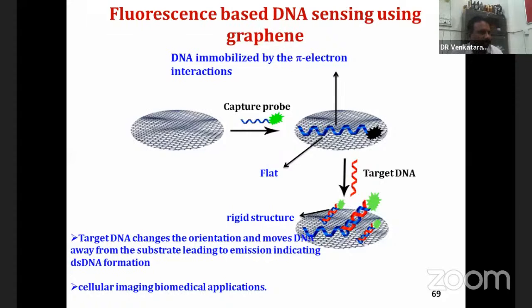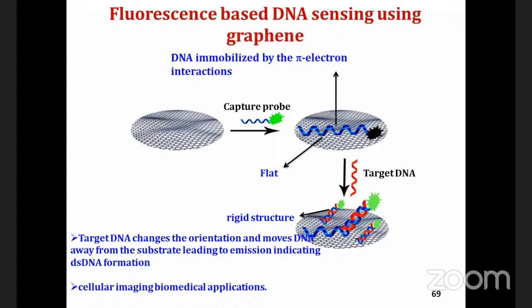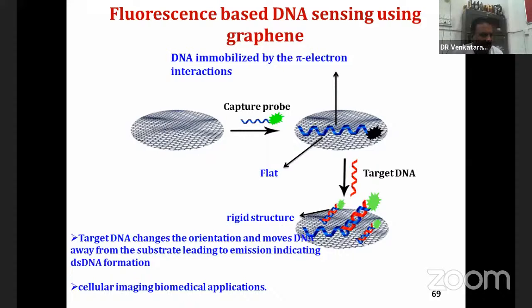Here, we put a single stranded DNA labeled with a fluorescent probe. Once it is in very close contact with the graphene surface, the fluorescence is quenched. After adding the target DNA, this single strand DNA reacts with the target and releases the probe away from the graphene surface. Thereby, it releases the fluorescent signal. That means the appearance of the fluorescent signal indicates the formation of double-stranded DNA on the graphene surface. This is called the on signal.